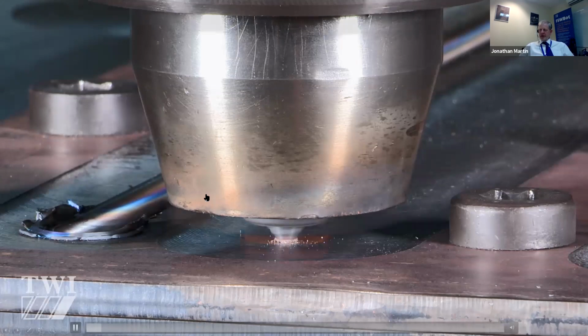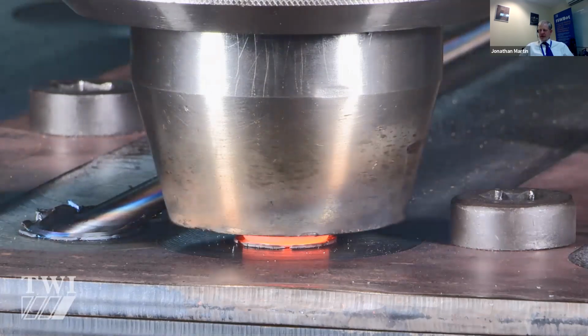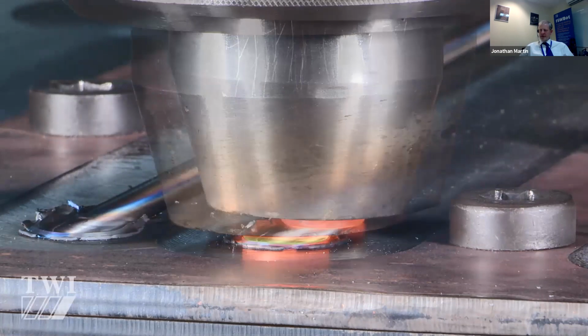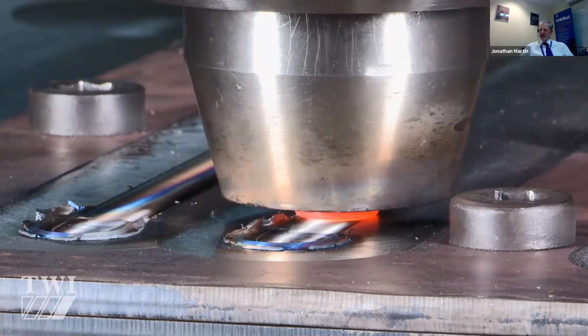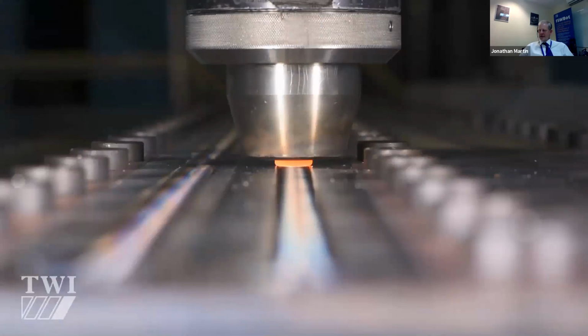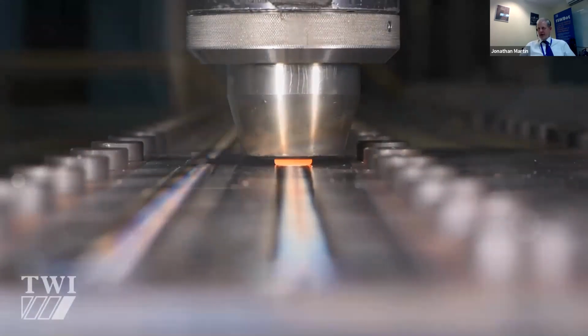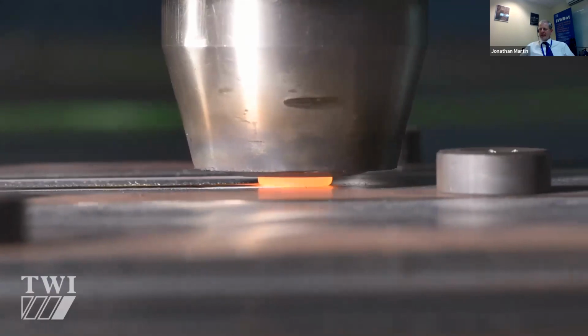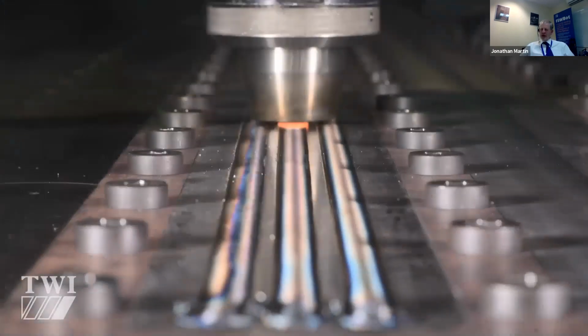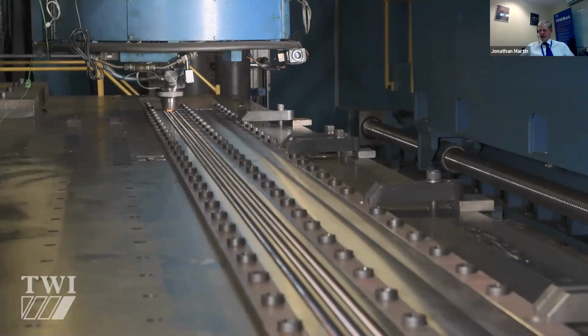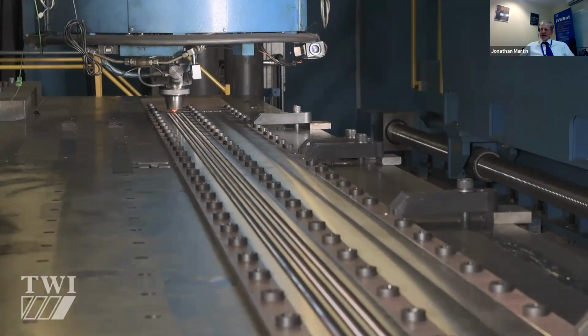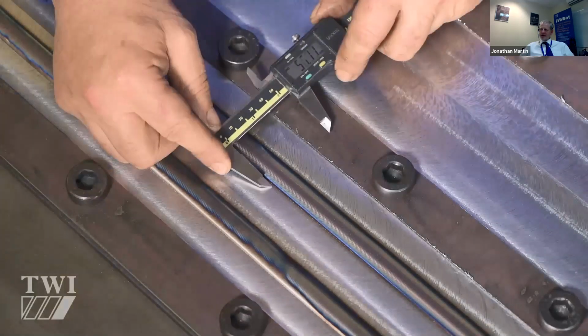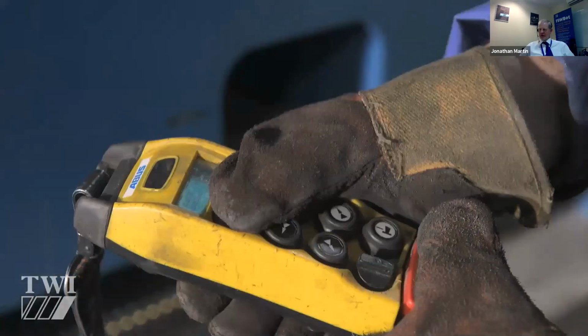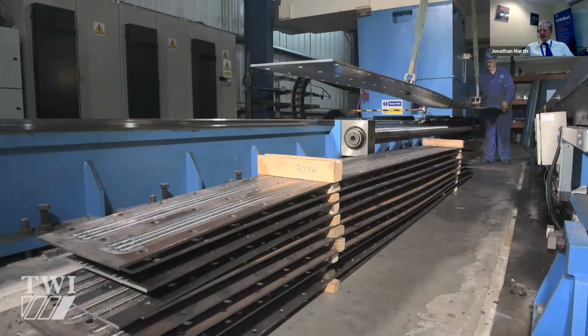So this shows the tool being rotated and being plunged into the material, heating the material up, getting it soft. The tool then transitions up the ramp phase, getting to full speed, to welding speed. So we're welding here at 300 millimeters a minute. So we're using an argon gas shield to protect the tool from oxidation. So you can see here the weld is now complete after 5 meters. We also measured the width of the weld cap to ensure that we're getting full consolidation of the weld itself.